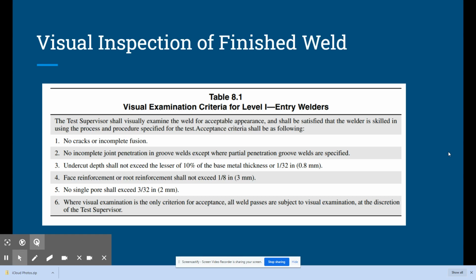No incomplete joint penetration in groove welds except where partial penetration groove welds are specified. Well, this is not a partial penetration groove weld, it's full pen. So we can't measure penetration with the backing strip on there, but we can also look for things like underfill. So if their cap is below the surface of the base metal, well, it'll be underfilled. That's going to fail a weld as well.